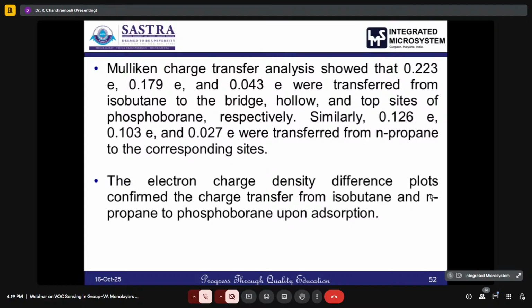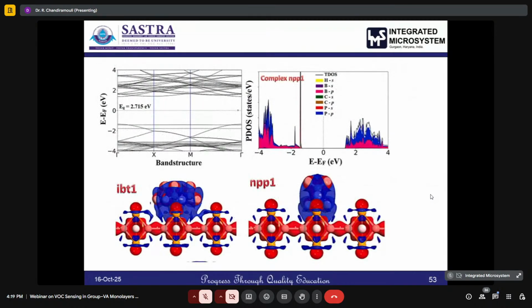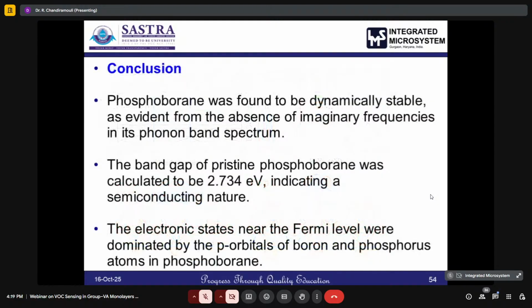Apart from that, the electron charge density difference is also explored to see how charge transfers from the base material to the target vapor and vice versa. The EDD, electron density difference, PDOS, and energy band structure are reported. The conclusion of this work is that phosphoborane was found to be dynamically stable, and the absence of imaginary frequency in the phonon band spectrum infers the dynamic stability. The band gap is 2.73 electron volt, and the electronic states near the Fermi level were dominated by the p orbitals of boron and phosphorus atoms.